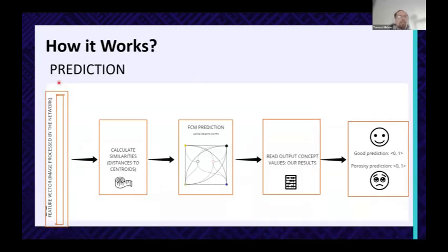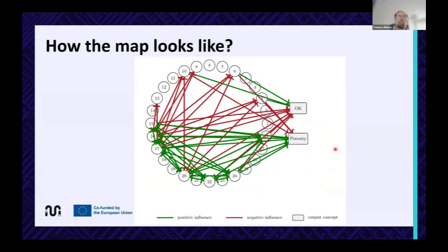And during the prediction phase, we also extract these features. We calculate similarities with the centroids, and using the already made map, we make an inference process with different types of activation functions. And as a result, we are given two results. One, if it is a good part, and the second one, if it's not a good part, so containing porosity. The map looks like this.